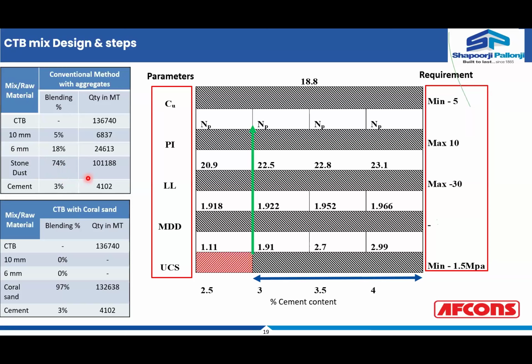And the beauty is that during the test, it was understood that coral sand contains some part of silica also. That means it has given the opportunity to even reduce my cement content from 3% to 2%. Though in the project we have not done that, because by the time it was recognized, it was too late to change the mix design.